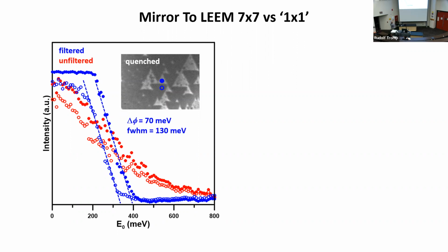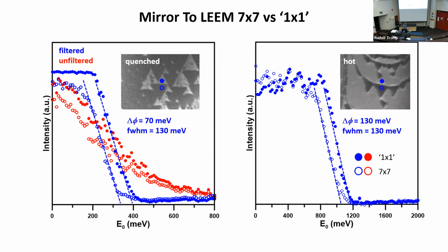So without energy filtering, we see this happening here. The reflectivity is 1 here, and then it drops over about an eV or so, because this energy distribution is very broad. When I turn the energy filter on, which means I put the slit in, this becomes symmetric and it becomes much narrower. So it's about 130 millivolts wide here. There are 2 different regions on the sample here, white and black, and they're shifted relative to one another by, in this case, 70 millivolts or so.